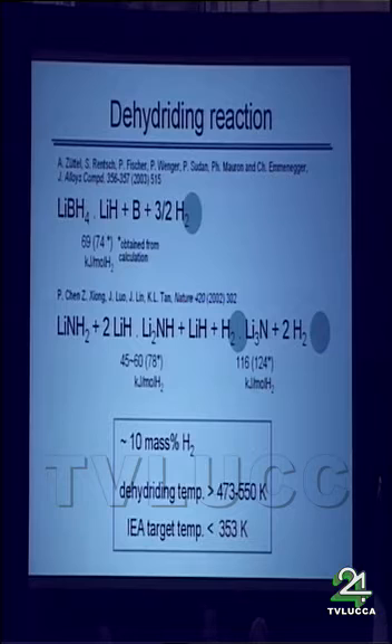In both cases, the hydrogen concentration is good enough. But the dehydriding temperature is sometimes up to 550 Kelvin, although the target of IEA is just 350 Kelvin. That's why we would like to thermodynamically destabilize these systems, considering the atomistic and also electronic structures. First, I will focus on the lithium amide system.